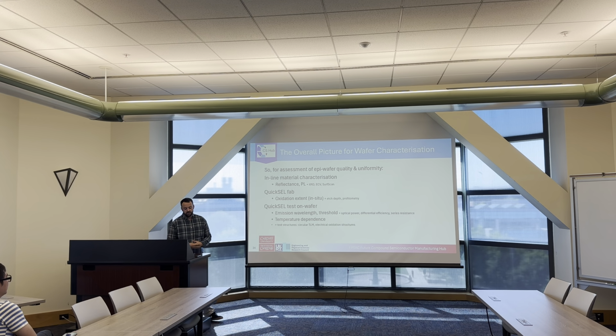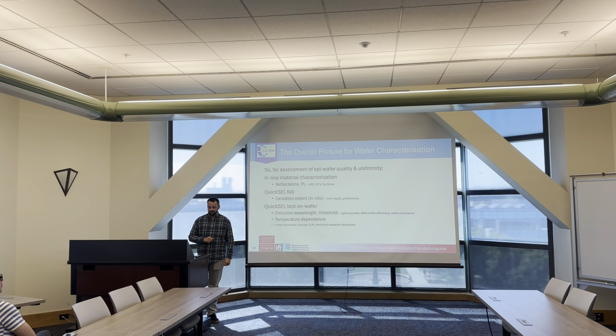Then the on-wafer test of VCSELs showed emission wavelength and threshold, but we can also look at optical power, differential efficiency, series resistances, and their temperature dependencies as well. And then finally, some other things that we include on the on-wafer testing, some different test structures, so circular transfer length method structures for assessing contact resistances and sheet resistance, and we also have some structures to measure the oxidation extent from electrical measurements. So essentially VCSEL mesas, but they don't lase, covered with metal, so you can measure the resistance change as a function of device size, and then fit to the data to see what the oxidation extent is.